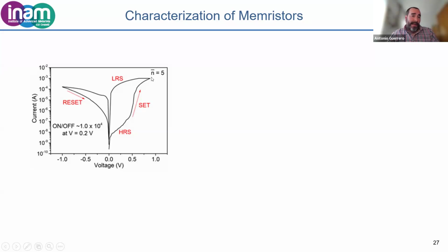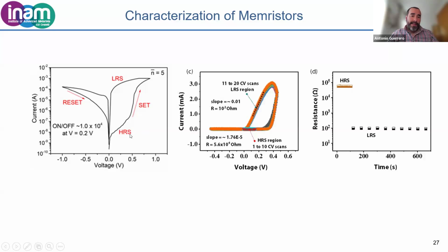And then, because it's a memory, what we want to happen is that when we go back, the device is still in this low resistive state, in which we can get a high current. So this means that for one given voltage, for example here, 250 millivolts, we can have a state that will give low current and a state that will give a high current. And these devices are called memristors because in this IV curve, basically what we are modifying is the resistance.